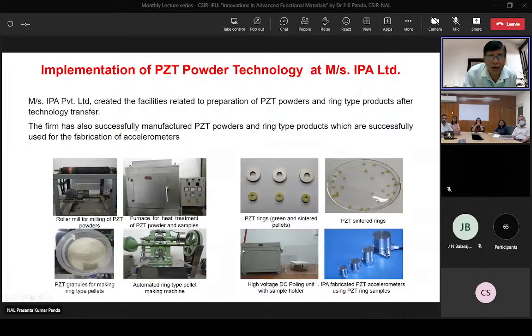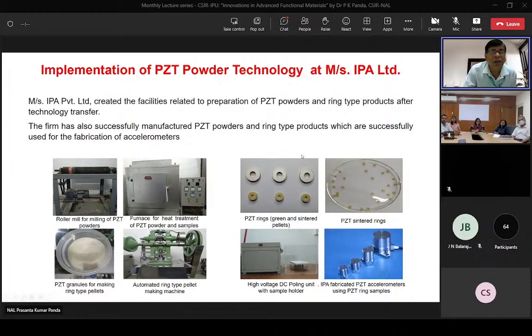Once the technology was transferred, of course just before COVID, the company went ahead in establishing the facilities. As you can see, these are the facilities available with the company. They have roller mills, furnaces for heat treatment of PZT powders, and a pellet tablet making machine. They make these powders, and you can see these are the green pellets, and after sintering you get these PZT rings. These PZT rings are also poled in this high voltage DC, and finally they fabricate PZT accelerometers. This is the final product.